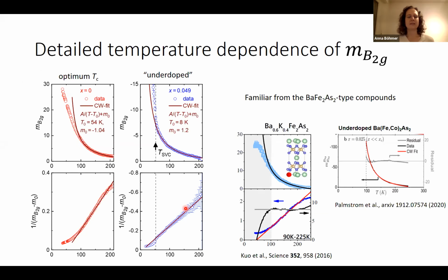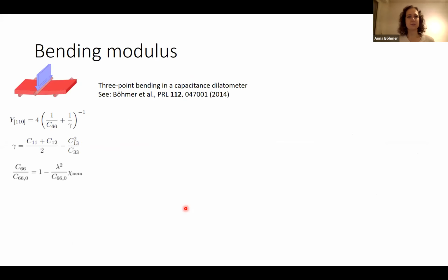But while we still don't really know about this prefactor, we thought we might try a different probe, the bending modulus, where this resistance prefactor does not enter. What we have here is the same equation that Matthias just used. The nematic susceptibility influences the elastic shear modulus. And with this coupling constant, this combination is dimensionless, and it has to be 1 at the transition. At the nematic transition, the shear modulus vanishes. So we have some handle on the units here. What we actually measure is not the shear modulus, but the Young's modulus, which also has some other non-critical elastic constants, and we try to get a handle on that using first principles calculations as input.